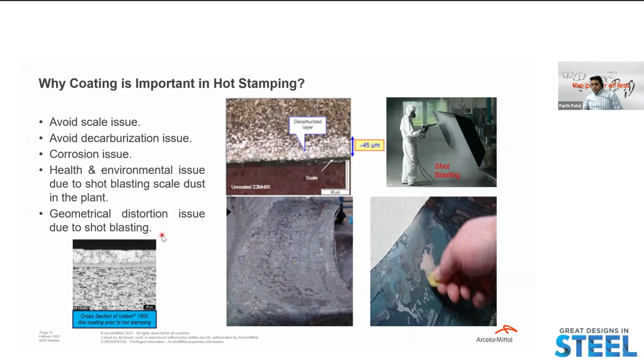Quickly jumping on the corrosion issue - obviously a lot of newcomers, new OEMs, or somebody new to hot stamping always wonder why do we use AlSi coating, why can't we do hot stamping without AlSi coating? Obviously, to avoid scale, if you use uncoated steel you will have a lot of scale during the heating process, and that will create a problem. So you want to avoid those scale issues, you want to avoid decarburization issues. If you heat at high temperature, you're going to lose carbon from the surface, creating decarburization issues. Another issue is corrosion, health and environmental issues, because with uncoated steel you'll have to use shot blasting, which creates a lot of health and environmental issues. Also, shot blasting might cause geometrical distortion in the part, creating another issue. That's why we need aluminum silicon coating for hot stamping, so it can avoid scale issues, decarb issues, and shot blasting issues, right?